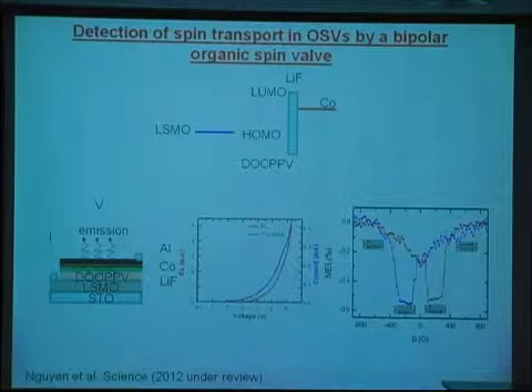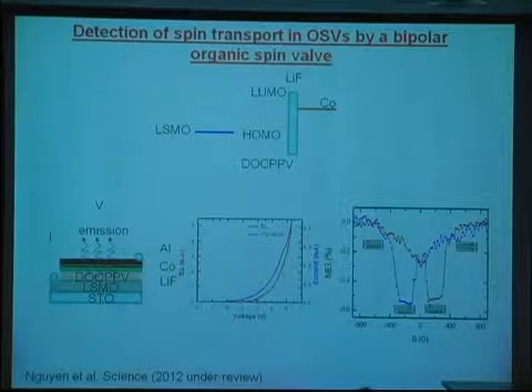So that's the reason why we are going to make the organic single crystal. We hope that we can enhance the spin diffusion length by 1 order of magnitude, from 50 nanometers to 500 nanometers, so that we can easily make the horizontal organic spin valves with this. So this is a new avenue for the community too. I think a lot of groups want to grow the single crystal and study the spin transport and spin injection into this kind of materials.